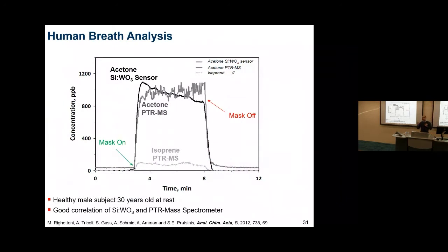Our sensor, if you're able to scale it up, should be around $100 as a device. You can see here that when you put the mask on, in black you see the concentration of acetone, and in gray you see the PTRMS measurement. So it's quite comparable, both with a little drift.